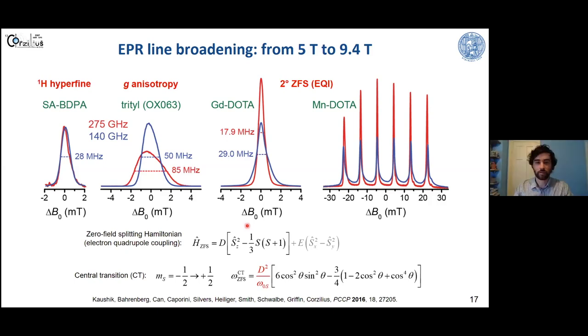All right. We have a question from Amrit. Why are low spin metals not used for DNP? Metals with spin a half will not have satellite transitions. So if only the central transition is used typically in these high spin systems for DNP, what about low spin metal systems? Yes. The reason is mostly that in these low spin systems with S equals 1/2, you have only one